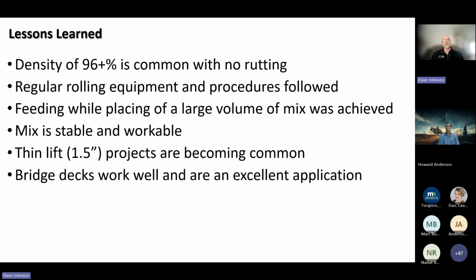So what lessons have we learned as a state and as an industry? With this material, getting densities above 96% is very easily achieved. That helps to facilitate a rut-free pavement. Regular rolling equipment and procedures have been followed very successfully. Feeding and placing of large volumes of mix was achieved. It does require diligent planning on the part of the contractor, but when they properly plan for that, having enough trucks and cycling properly, they've been able to maintain a good, smooth, steady flow of material.